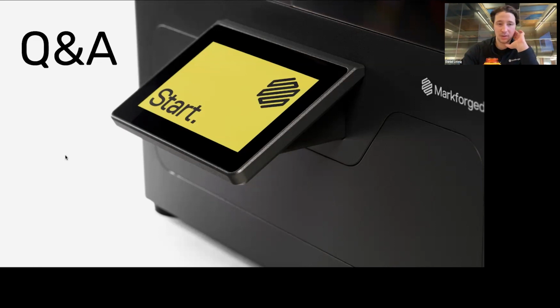What are the largest dimensions we can provide? If you have a long skinny part, you can probably print it up to about 250 millimeters. Our build size is about 300 wide and it shrinks about 20%, so 250 is the rough number there. But it depends. You wouldn't want to print a full build size thing that's 250 millimeters long. But if you have a longer, skinnier part, it's certainly feasible.